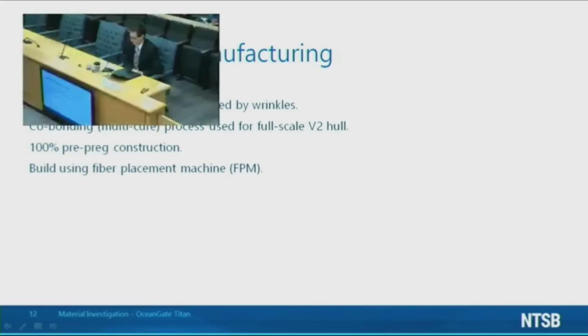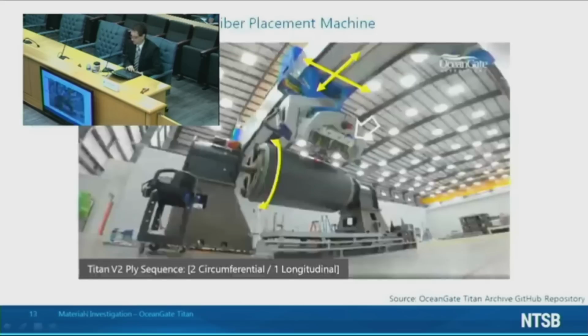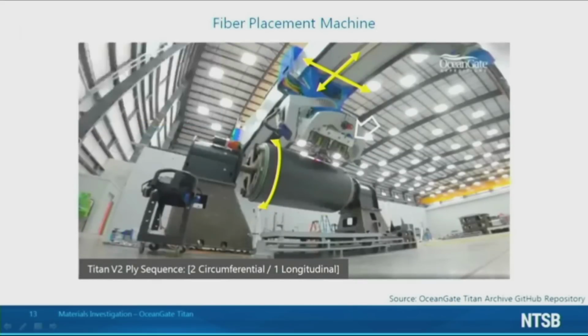After building a couple of test rings to test the viability of the co-bonding process, OceanGate proceeded with building a full-scale version 2 hull for Titan. The full-scale V2 hull was manufactured by automatic fiber placement. This is a robotic system that, in this case, was probably attached to an overhead rail and trolley system and contained multiple spools of pre-preg tape loaded into a fiber placement head.